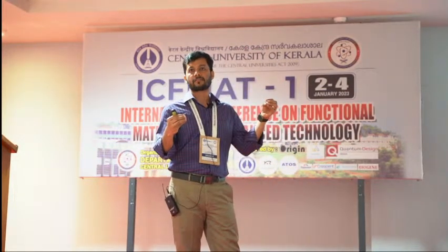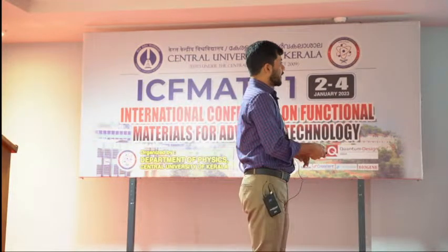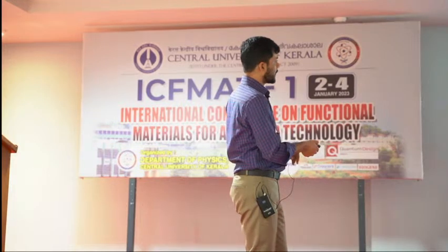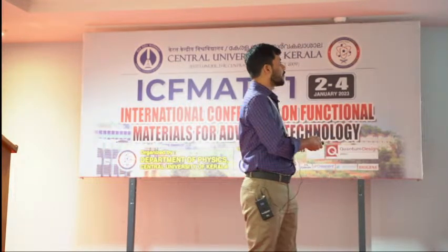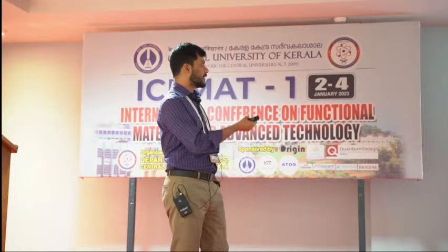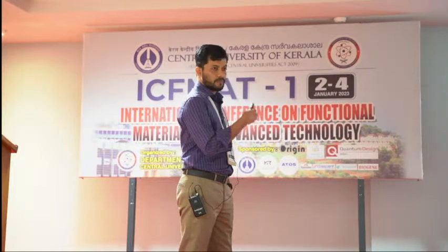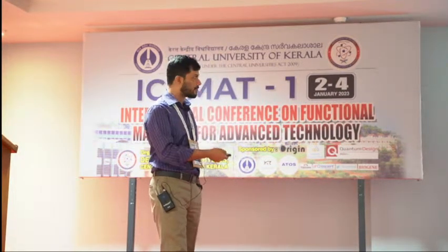So we changed the length of the nanowires and looked at the enhancement. As you can see from this figure, the electric field is enhanced much better for smaller aspect ratios. That means shorter wires will give you much better enhanced electric fields. So this is one criterion that you want to have.